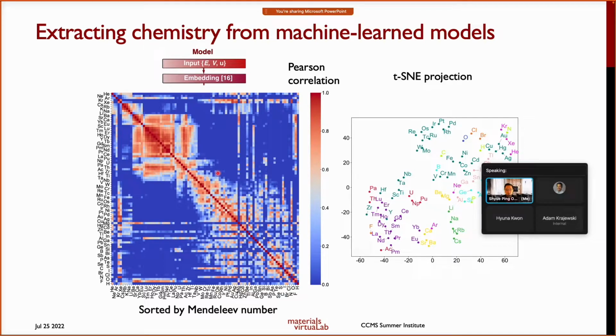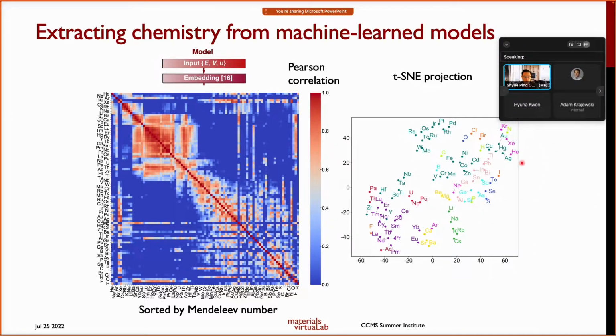So we know, for example, that lithium and sodium have very similar chemical properties. And here, the embedding vectors have a very high correlation with one another, even though we didn't start off using highly correlated embedding vectors, right? So the machine learning model has naturally learned a chemistry trend. We can also do what is called a t-SNE plot, and again, what you notice is that here all your elements that are very similar chemically actually are clustered together in this t-SNE plot, right? For example, all your alkali metals are all over here, your alkaline earths are a bit more spread out, but all your rare earths are all over here, and you notice that these are all things that you would expect in terms of the chemistry similarity of all these elements, okay?